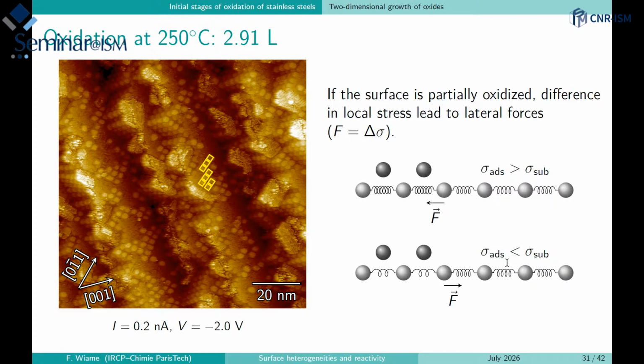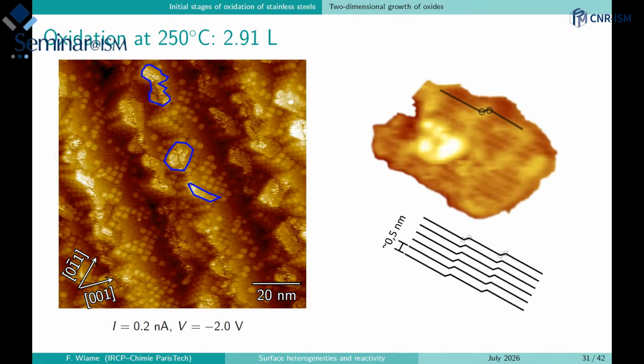We can also see other structures which are appearing on the surface, which are also at reactive sites on the step edges, which can be identified as iron oxide. And this is confirmed by the fact that this is the exposure for which we have the appearance of iron oxide in the photoemission spectroscopy measurement. And so we know that what is appearing at this stage is in fact iron oxide. And so we have iron oxide, which is appearing very fast also at the very beginning, before the chromium oxide is finished, which is a problem for the resistance to corrosion of the system, because the idea is that the chromium oxide should be protecting the surface